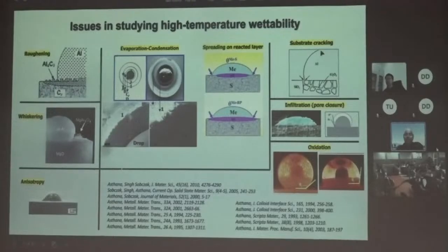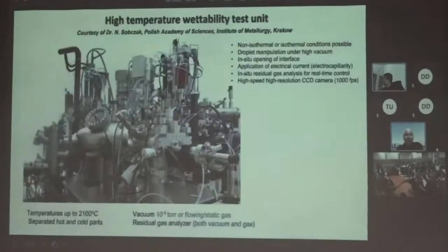Another thing we see is cracking because of expansion mismatch between the liquid and the solid. The classic example is aluminum in contact with silica. And that reaction gives the volumetric expansion and the cracking. So essentially, when you have the liquid droplet to measure the contact angle, the liquid is actually penetrating, and the angle that you measure is incorrect. So all of those issues are very difficult to actually experiment with.